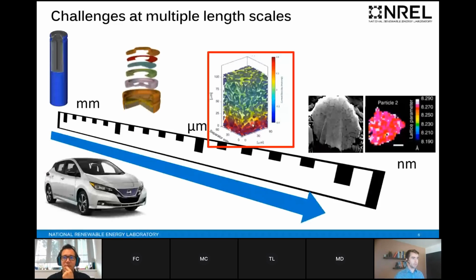And transport limitations, as you can see in this figure, are a major concern. So as Mehdi covered in his last talk, these lithiation gradients can occur even at very low C rates, but we're talking about full charging in about 10 minutes, so that's about 6 C. So the lithiation gradients can become extremely severe. And with those lithiation gradients, the local potential versus lithium in some regions, particularly near the separator, can very quickly go below 0 volts and cause lithium plating. So lithiation gradients are a big concern. And we wanted to understand the lithiation gradients and also the behavior of graphite within thick electrodes, so high energy density electrodes that are favorable for range in the electric vehicle.